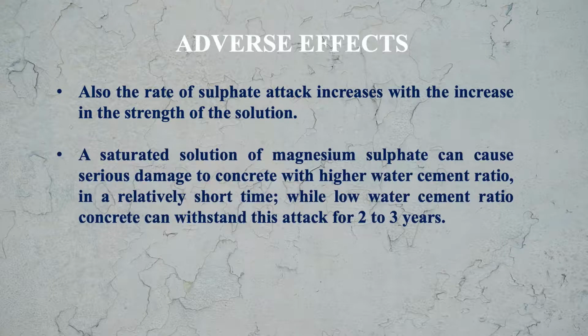A saturated solution of magnesium sulfate can cause serious damage to concrete with higher water cement ratio in a relatively short time. You can see here that it can harm more in relatively short time, while lower water cement ratio concrete can withstand this attack for 2 to 3 years. So that is the effect of the water cement ratio.